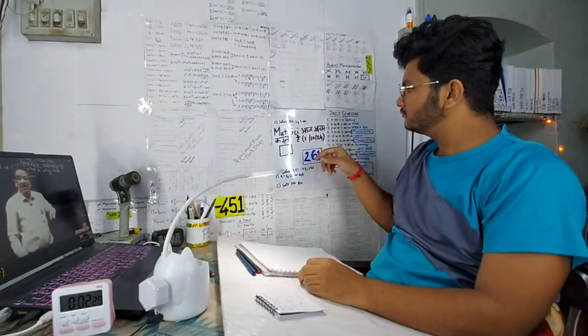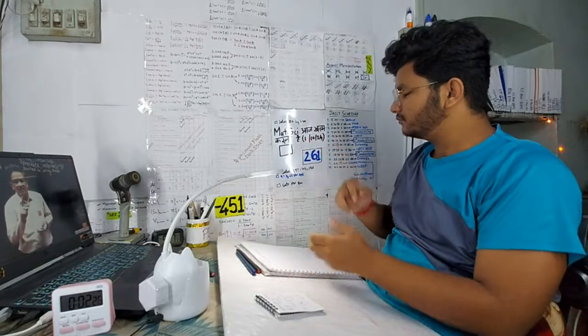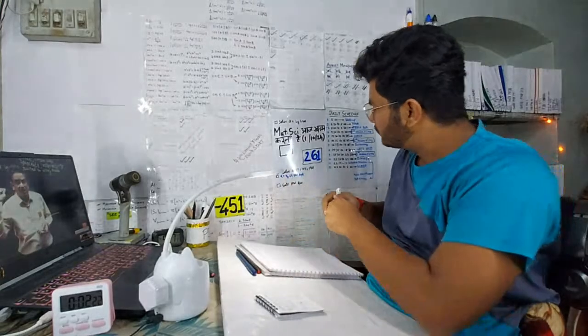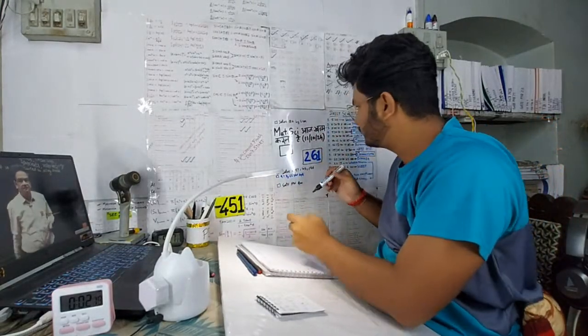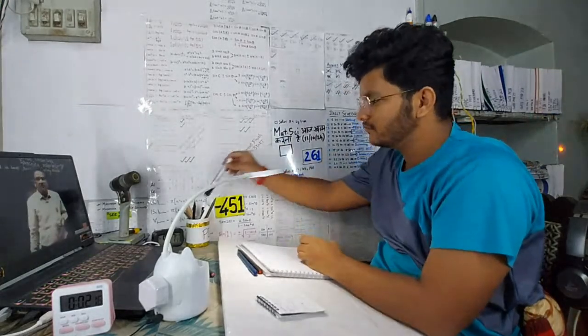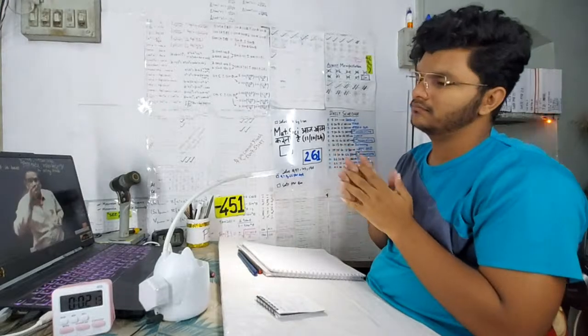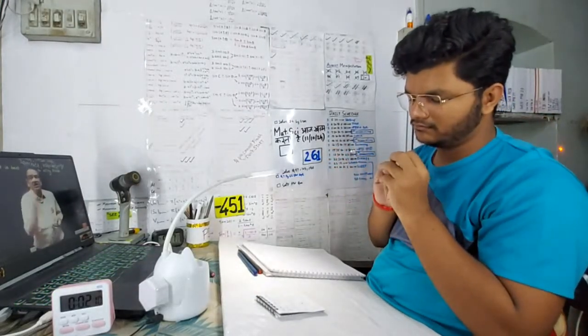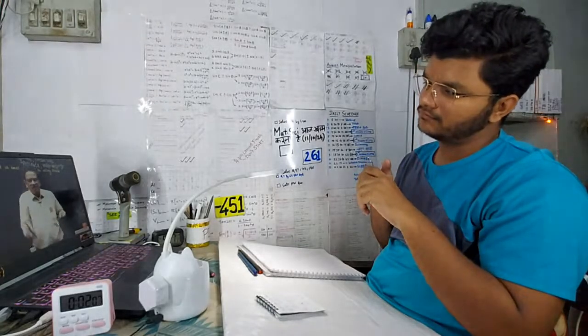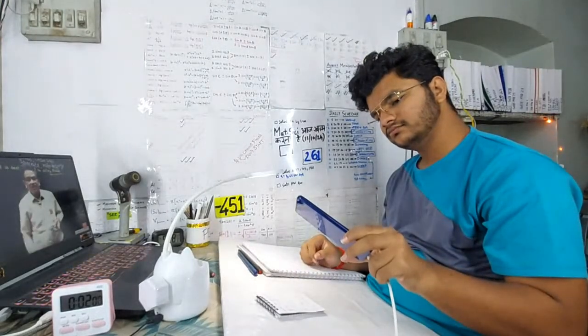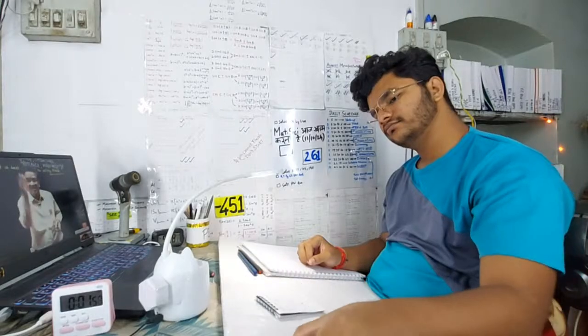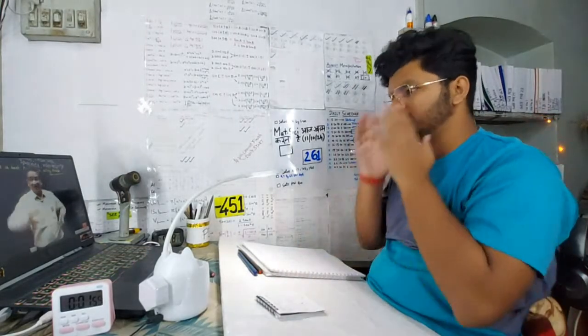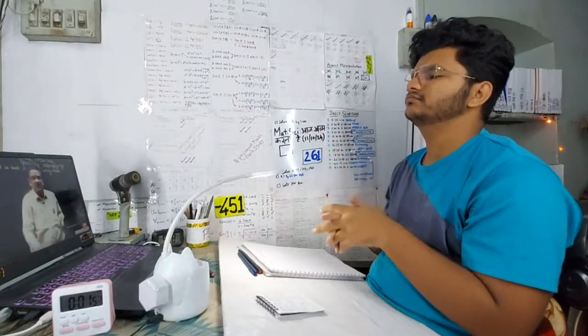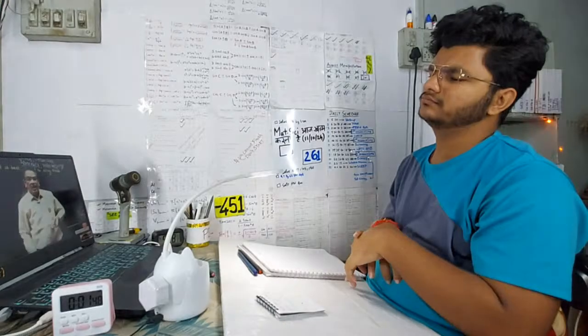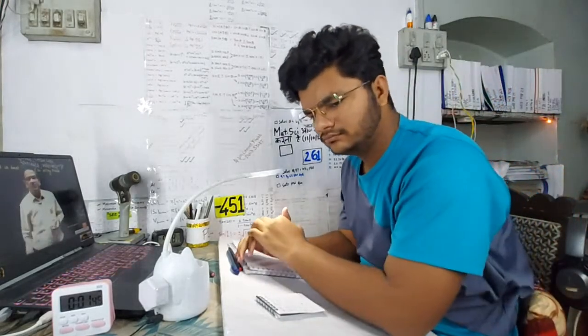That is the reason why surface hardness and toughness requirements are both fulfilled in one place. Number one. And since you develop a hardness more than that of martensite, quenching is not needed. Number three, nitride layers are non-metallic in nature. Because they are non-metallic layers, they reduce coefficient of friction and increase corrosion resistance as positive side effects. In addition, nitride formation induces surface compressive residual stresses. Due to these stresses, nitrided surfaces have improved fatigue resistance or fatigue life. Operating temperature is normally in the range of 500 to 550 degrees centigrade for this process.